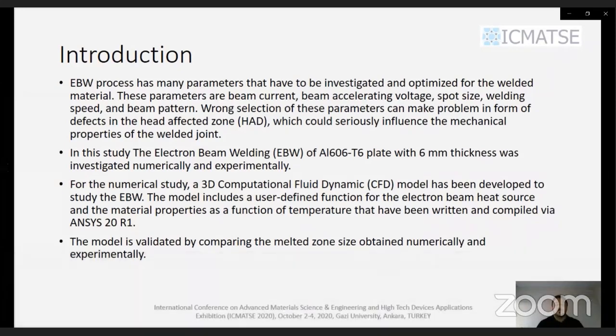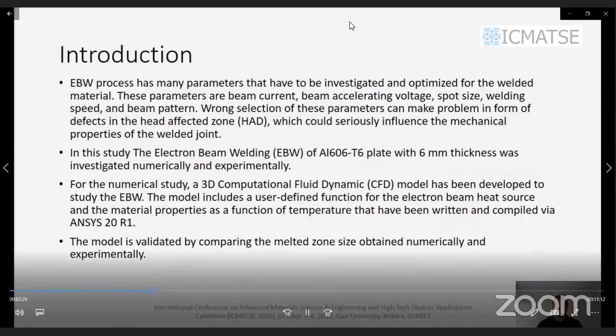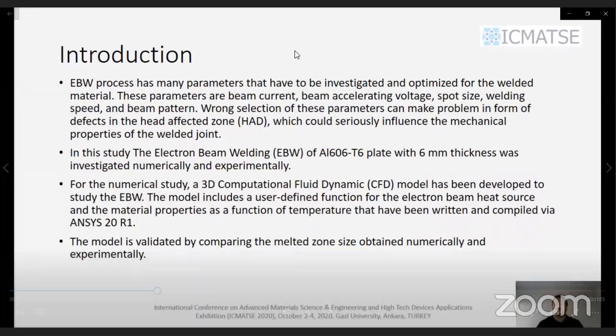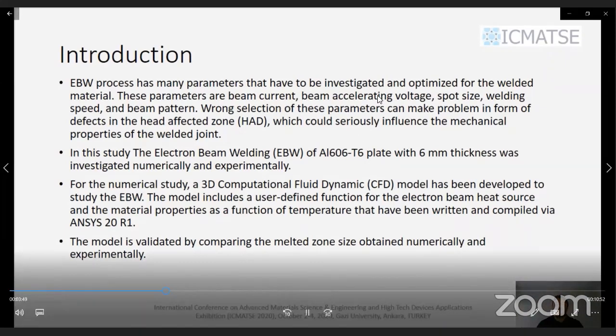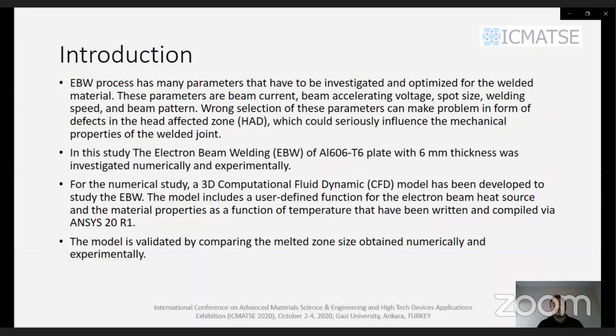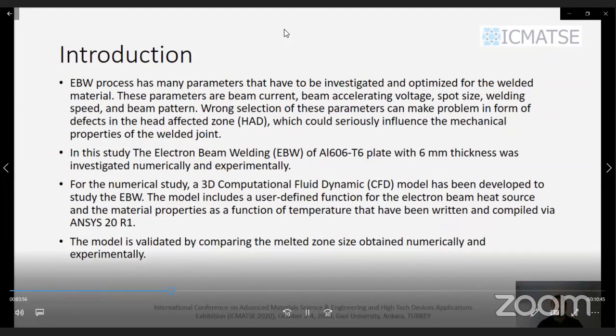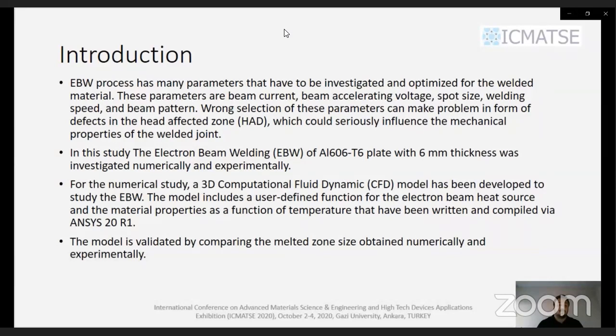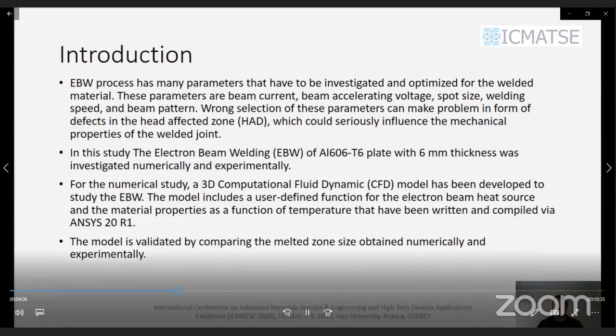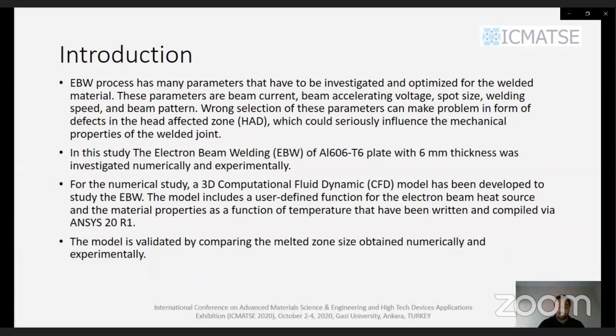In this study, the electron beam welding of aluminium 6061 with the T6 condition plate with 6 millimeters thickness was investigated numerically and experimentally. For the numerical study, a 3D computational fluid dynamics model has been developed to study the electron beam welding. The model includes a user-defined function for the electron beam heat sources and the material properties as a function of temperature that have been written and compiled via ANSYS 20 R1 software. The model is validated by comparing the melted zone size obtained numerically and experimentally.